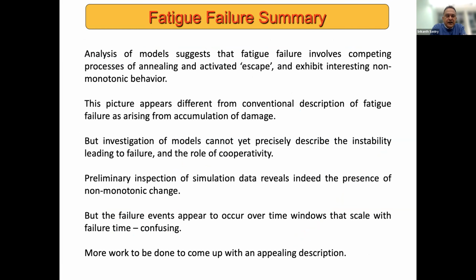So the summary of the results for fatigue failure is that analysis of models suggests that fatigue failure involves competing processes of annealing and activated escape and exhibits interesting non-monotonic behavior. This picture appears different from conventional descriptions of fatigue failure as arising from accumulation of damage. But investigation of models cannot yet precisely describe the instability that leads to failure and the role of cooperativity, and that's something where we have to do more work. Preliminary investigation of simulation data reveals indeed the presence of non-monotonic change, but the failure events appear to occur over time windows that scale with the failure time, which is a little confusing. And so we have more work to do to come up with an appealing description.